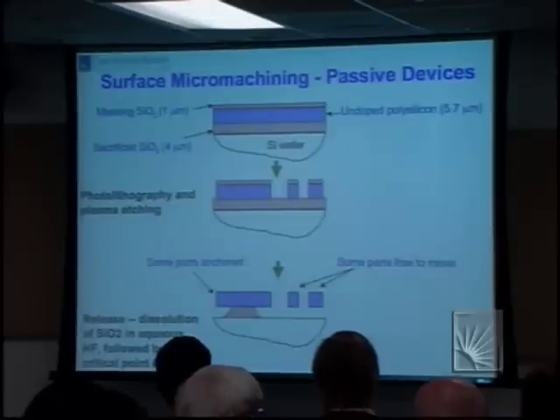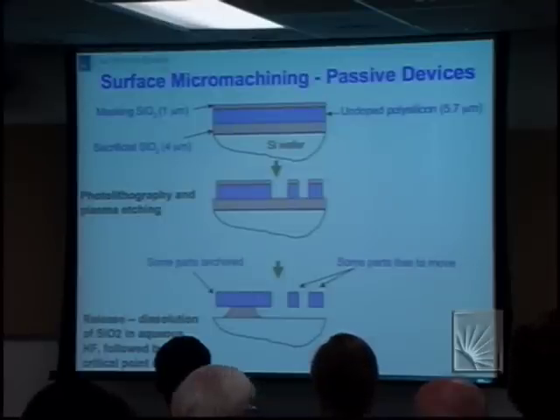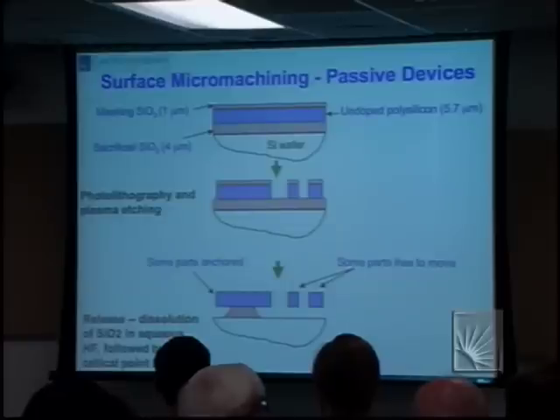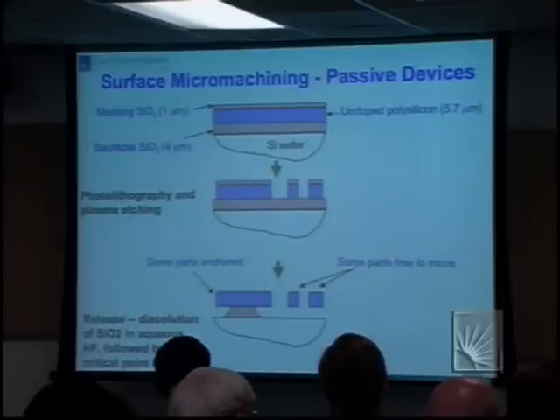There are two types of so-called micromachining. This is, again, a jargon word. This is either, as shown here, surface micromachining, which is an additive technique in that the silicon wafer is just a substrate which supports the device. Bulk micromachining is a subtractive technique. You take a silicon wafer and etch away in selective ways. I won't talk at all about bulk micromachining. All the work we've done has been surface micromachining using the class 100 MFL just about 100 yards from here.